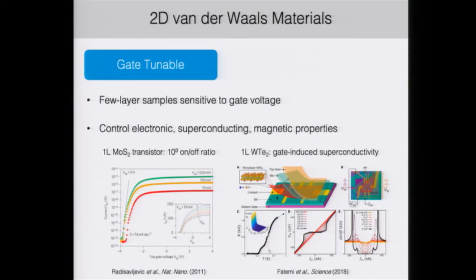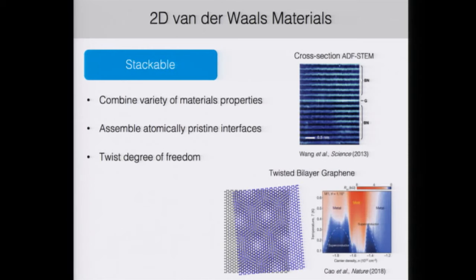And these are some examples. Here's a monolayer molybdenum disulfide transistor, which has a 10^8 on-off ratio, so it's very, very sensitive to gate voltage. Also, last year, our group demonstrated that monolayer tungsten ditelluride can be gate-induced into superconductivity, which has also been observed in other layered materials. So you have a very wide range of material parameters that can be tuned in a single device just by applying some volts. And finally, van der Waals materials are stackable.